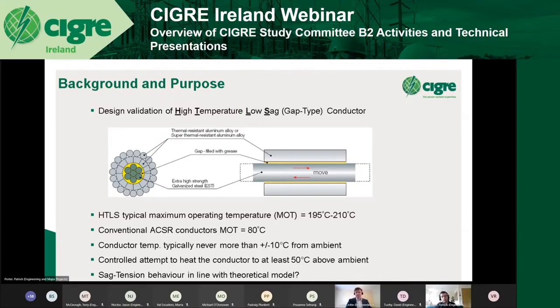So with HTLS conductors, we would refer to them as non-conventional in that they're designed to operate at much higher maximum operating temperatures, typically upwards of 200 degrees Celsius, whereas the conventional ACSR conductors, which the majority of the transmission grid here in Ireland was constructed with and still operates under today, would have an MOT of no greater than 80 degrees Celsius. If we look at conductor temperatures in the field, on any given day on a typical transmission line, they're typically never any more than plus or minus 10 degrees Celsius away from the ambient temperature on the day, and that would be under normal loading conditions.